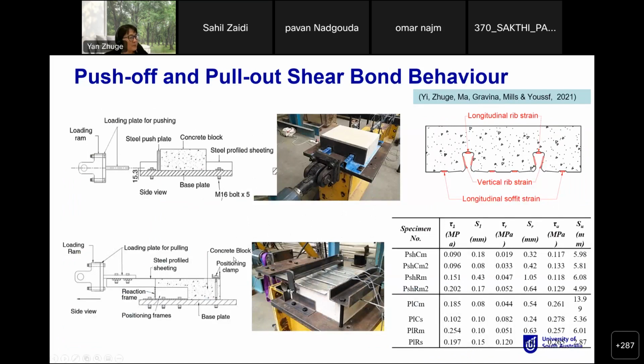So we did some different testing. The first group of testing we did was push off and pull out shear bond behavior. Because you can do the full scale testing, you want to understand what the bond performance of these composite structures is. We did a literature review and found 2 different tests available, one is push off and the other is pull out. We're not sure which one gives a better result, so both methods were trialed, and we want to see the difference in the results.